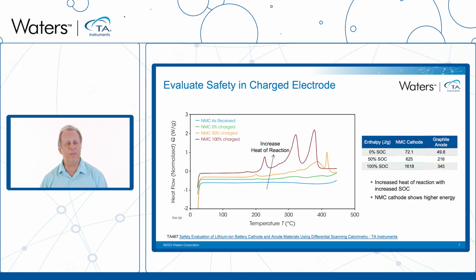And what's quite obvious here is that the state of charge has a huge impact on the complexity of the exotherms that you capture and the quantity of heat evolved. And on this right-hand side, we have a chart which shows that for the NMC cathode, we move from essentially no exothermic activity in the as received material, and then we proceed through 72.1 joules per gram all the way up to the 1.6 kilojoules per gram.